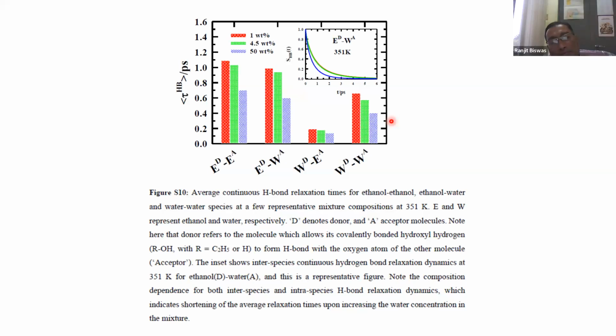See, I found one thing. I'm writing a paper on that. Chandler and other people say water-DMSO hydrogen bond is twice as strong as water hydrogen bond, which is stupid, because DMSO oxygen negative charge is about -0.4. Water is -0.8, right? So it cannot be strong, but it is effectively strong through hydrogen bond lifetime. The reason is that the methyl groups are forming a cage. The hydrophobicity of the methyl groups is forming a cage, and that is holding the hydrogen.